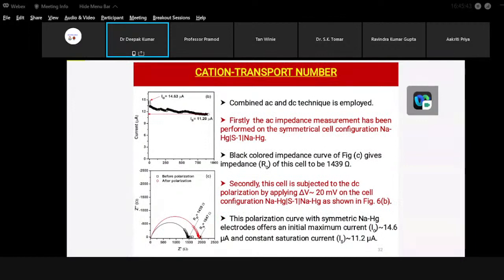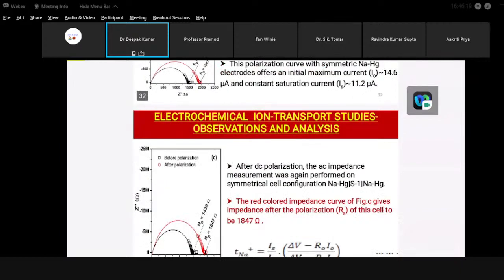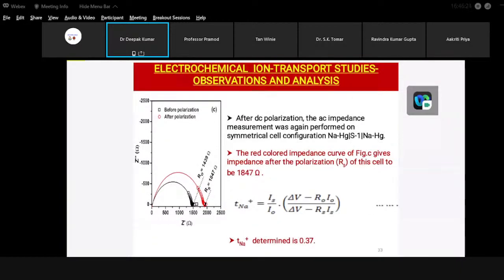The cation transport number is also measured using the Vincent method, which is a combined AC and DC technique. For such a technique, impedance has been taken before the polarization. That impedance is recorded to be almost 1439 ohms. After this, the electrolyte is polarized and current is monitored as a function of time, and the saturation current and the initial current are utilized in the Vincent formula. And what we observe is that we have determined the sodium ion transport number to be 0.37, which is quite good enough for realizing electrochemical systems also.